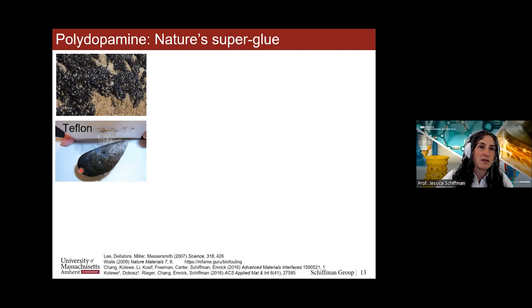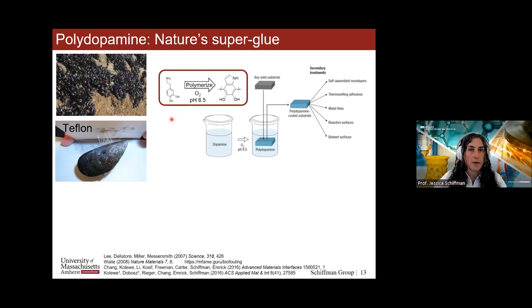And here, the polydopamine or the DOPA gets extruded from the mussel, almost like a polymer extrusion process. And when it mixes in the presence of certain ions and things like this, the proteins are able to attach very irreversibly, even to the fluorinated surface of Teflon. And so how does this work? Well, a very simple chemical that we can buy from Sigma Aldrich is this dopamine. And when we polymerize it in the presence of oxygen and at a pH of 8.5, it actually makes a self-limiting coating called polydopamine. And again, over a decade ago, it was shown that we could use this polymerization technique on many, many different surfaces.